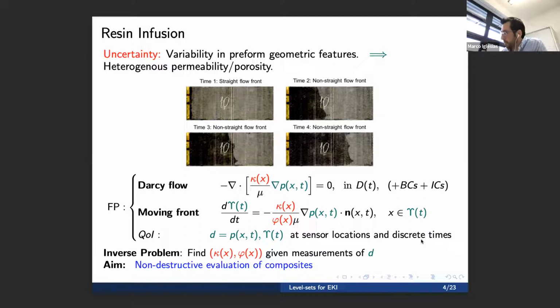So the preform, which you can see an example of a rectangular reinforcement here, it's a porous medium. And the permeability and porosity of this porous medium is related to, again, this alignment of fibers, how the fibers are placed. And because the robotic system is not perfect, there might be some variability in these properties. And what we would like is, during the infusion of resin, to capture this variability,